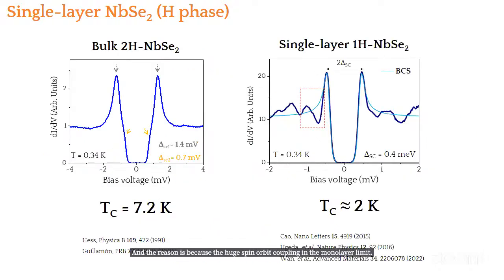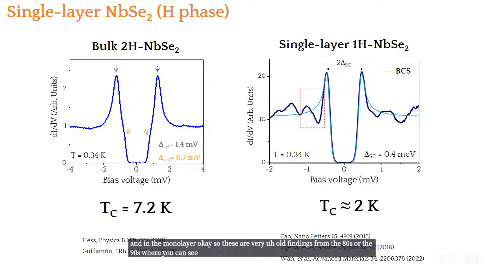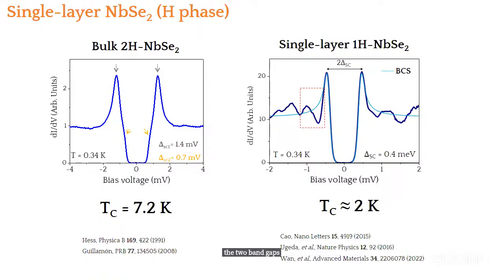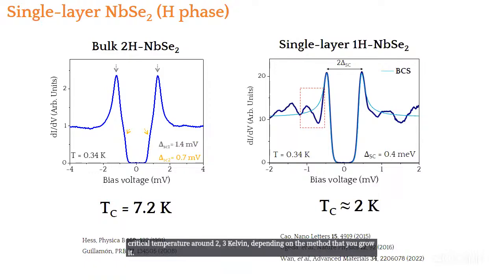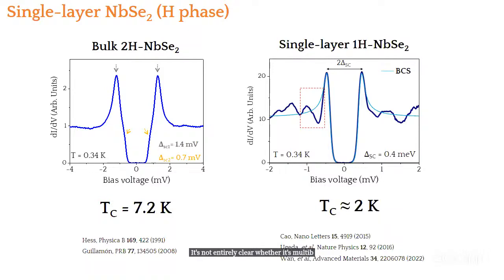Okay, concerning superconductivity, this material is superconducting both in bulk and in the monolayer. Okay, so these are very old findings from the 80s or the 90s, where you can see that the bulk 2H niobium diselenide is a multiband superconductor. Here you can see the two band gaps. Here is one, there is another one here, and the critical temperature is around 7 Kelvin. Okay, so if you grow just one layer of the material, here's the result. The system is also a superconductor, but with a much smaller critical temperature, around 2-3 Kelvin, depending on the method that you grow it. It's not entirely clear whether it's a multiband superconductor or not.